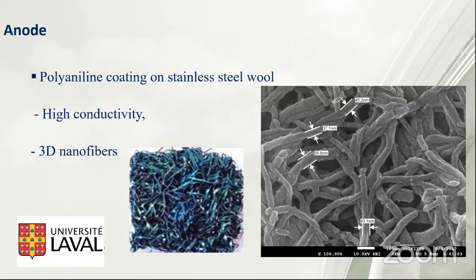I'll give some examples of highly conducting polymers. First is polyaniline coating on stainless steel wool. As I mentioned, we need a material with very high surface area. So what we developed is we used stainless steel mesh and coated polyaniline using electrochemical deposition. After the deposition, you see here we formed nanowires on this surface, around 30 to 60 nanometers. These are very thin nanowires for electron conduction. Since it has very high electrical mobility, we found this is the best material, and we further analyzed it in microbial fuel cells.